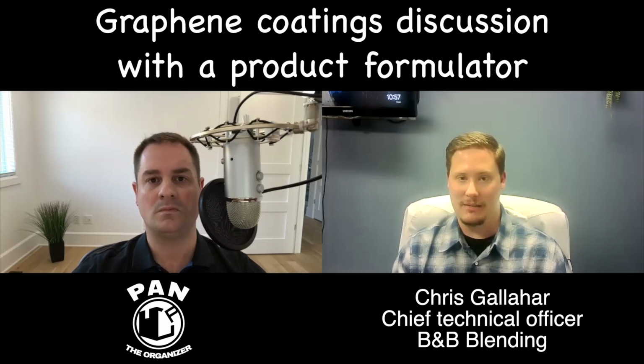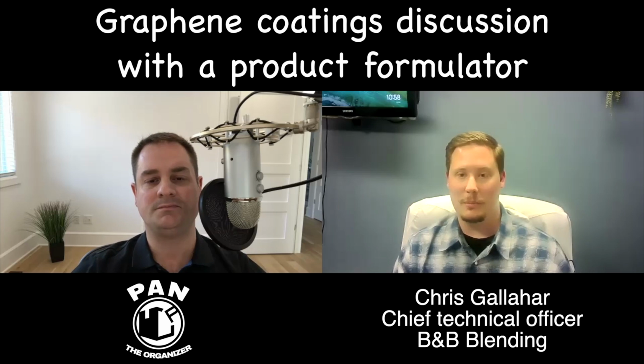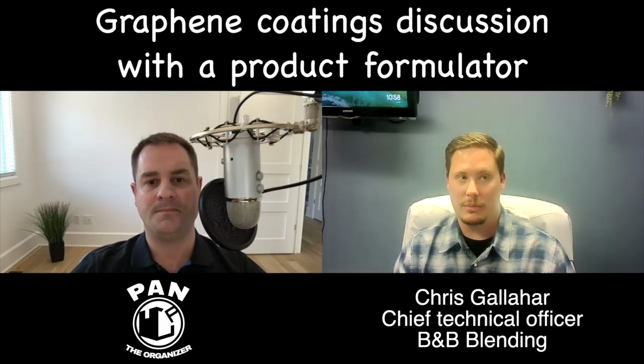If anything, maybe you're measuring just exactly the top surface of it. But the reality is the coating is so thin and such a veneer, it's not going to have any sort of real framework to be conducting any thermal heat transfer through, right? So there is definitely a case to be made about graphene oxide and graphene as heat transfer coefficient efficient molecules, right? But you're going to have to do that on a much more macro scale. You're not going to be able to do that on something that's literally molecularly bonding to the surface and it's only a couple atom layers thick. So to me, the thermodynamic piece isn't incorrect. It's just not applicable in this situation.